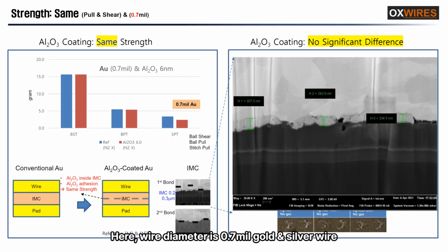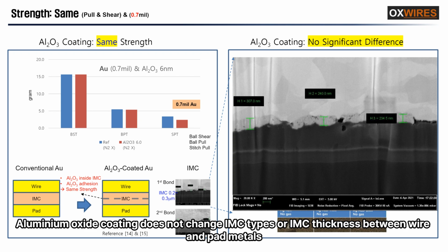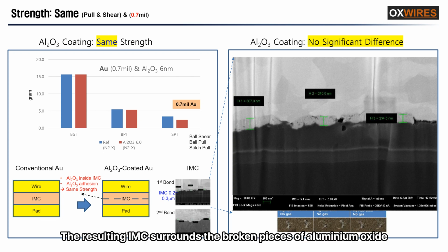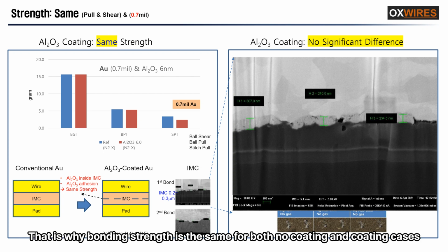Here, wire diameter is 0.7 mil gold and silver wire. Almost same strength data were obtained. Aluminium oxide coating does not change IMC types or IMC thickness between wire and pad metals. The resulting IMC surrounds the broken pieces of aluminium oxide. And aluminium oxide has a good adhesion to wire and pad metals. That is why bonding strength is the same for both no coating and coating cases.